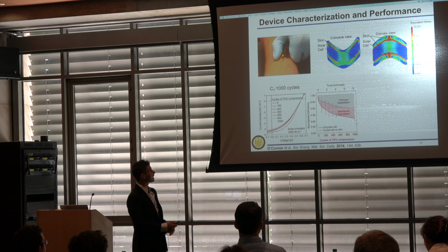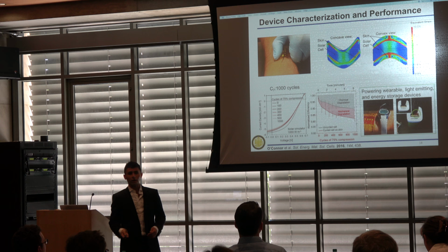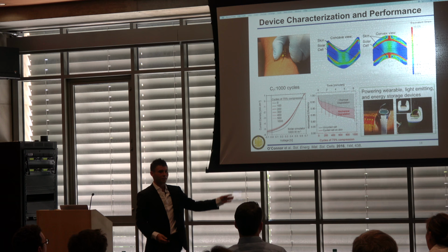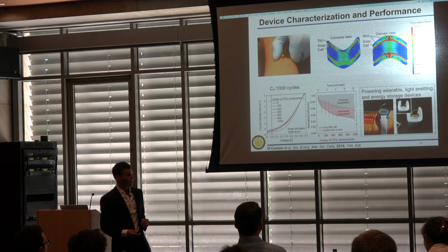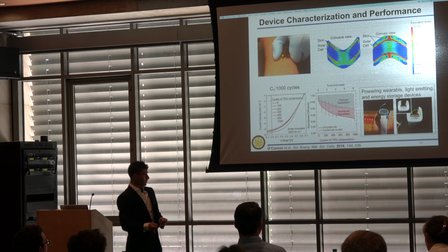We then used this device to power other wearable electronic devices. We used it to power a digital watch, an LED, and then start charging a portable battery. And we did it using natural sunlight. So I actually dragged the whole setup out away from the solar simulator out on the bridge here and powered this digital watch. And the digital watch is a proxy for something like a wearable biomedical sensor, like the ones perhaps being made down the hall here, which use about 100 microwatts. And this is on the same order of power demand as the digital watch here.